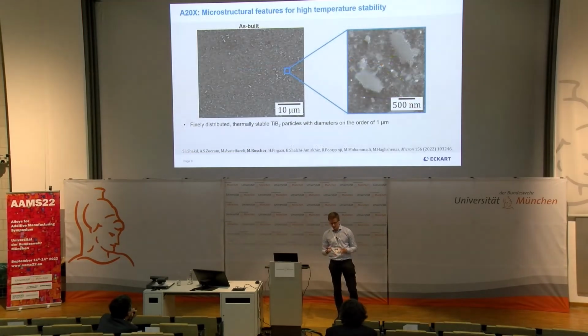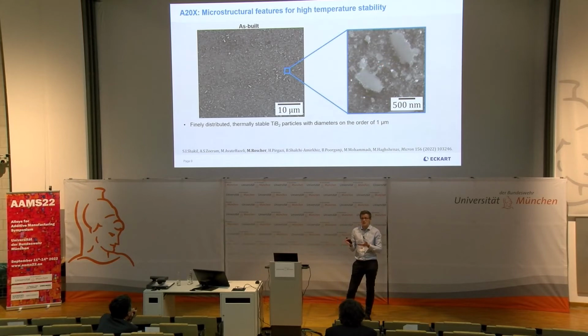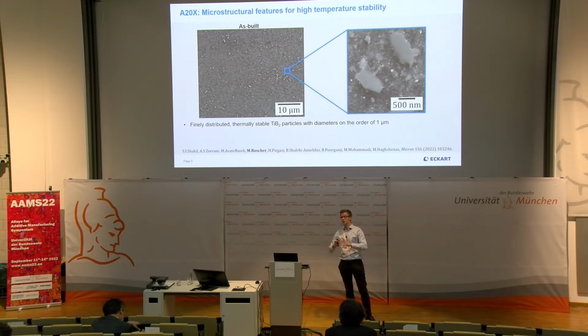So the question that follows is, why does this aluminium copper alloy have much better high temperature properties than other conventional high strength materials? There are two factors. The first one is related to the presence of titanium diboride particles. As we can see in these micrographs, the titanium diboride particles are relatively homogeneously distributed in the as-built material. These particles represent obstacles to dislocation motion, and more importantly, they do not coarsen during temperature exposure.